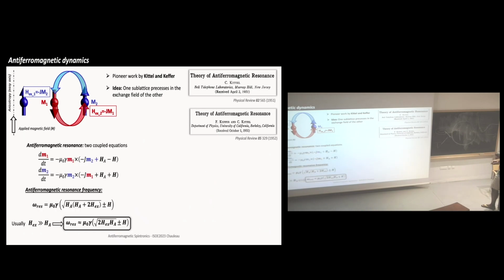So now, if we consider antiferromagnetic resonance, then you go to two coupled equations where you have to add the exchange field of one sublattice to another. If you do this, then you solve the equation. You can find the eigenfrequency, and what you have is a resonance frequency which scales with the square root of the exchange times anisotropy. And this time the exchange in an antiferromagnet can be in the hundreds of Tesla. So that means it's directly in the sub-terahertz and terahertz ranges.